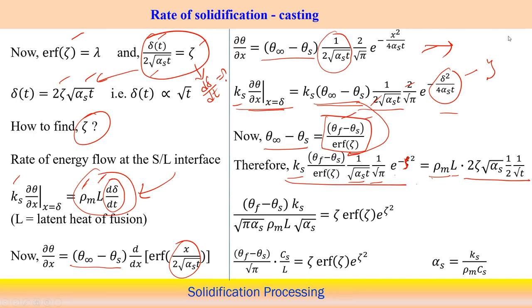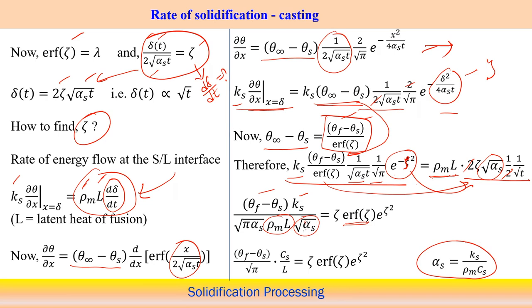Then, rho m l into this, and making the further balance, we will be able to get theta f minus theta s, then k s here, and then we take rho m l to the other side, root over pi alpha s, and the other alpha s, root over alpha s, and on the other side the 2 balances. Zeta equals the error function of zeta on this side, and then e to the power zeta square. So finally, we are getting theta f minus theta s, because we know that alpha s equals k s by rho m c s. We put it in, then we will be able to get C s by L equal to zeta, this kind of equation.